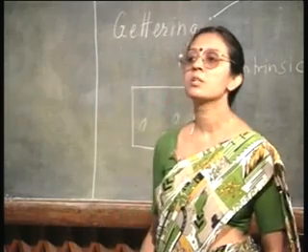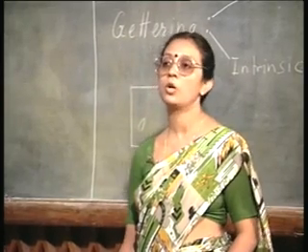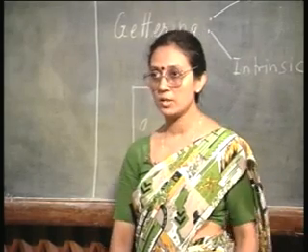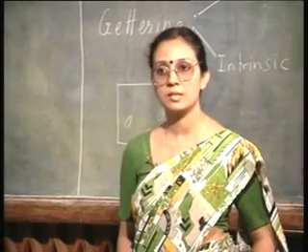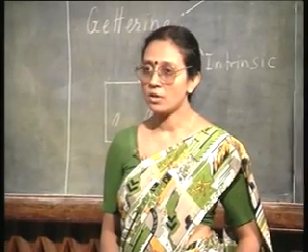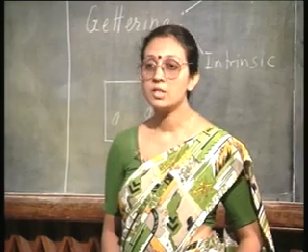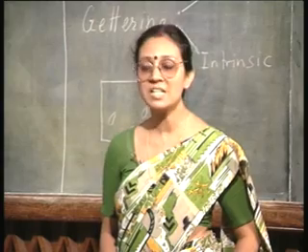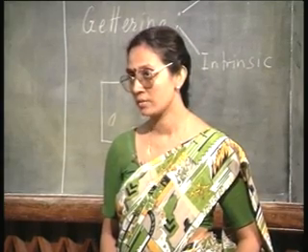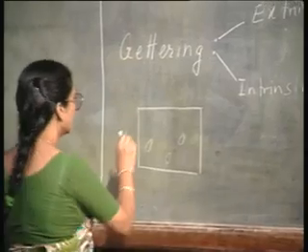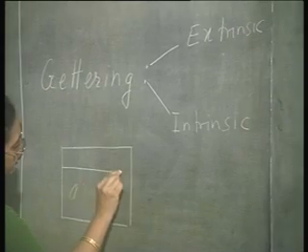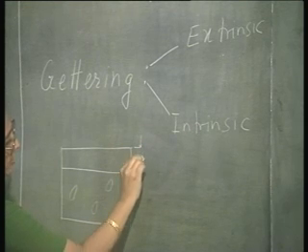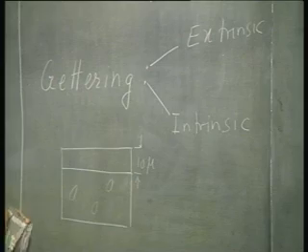So, you can use the oxygen precipitates also, which are already present in the crystal, that is why it is called the intrinsic gettering. You are using what is inherently present in the crystal itself. That can also be used to your advantage, provided you make sure that these precipitates are not threatening the active region of the device. So, your device is contained in the top, let us say about 10 micron, and the rest of the portion